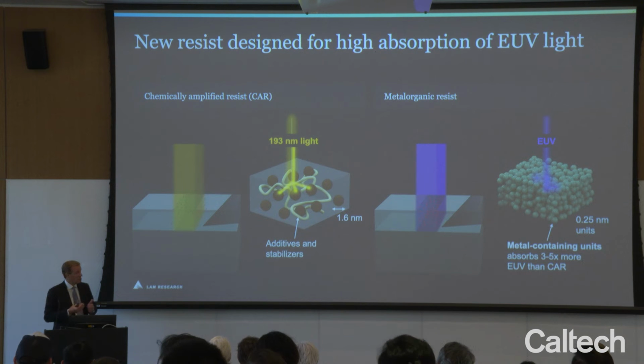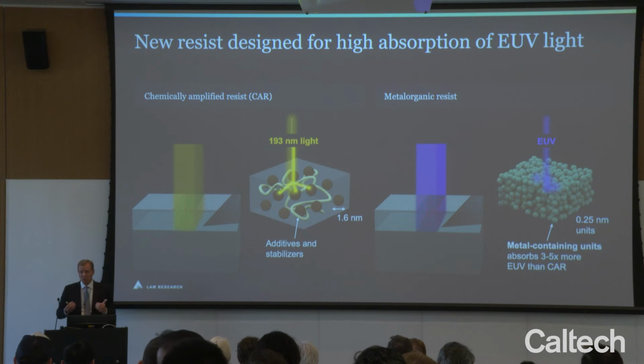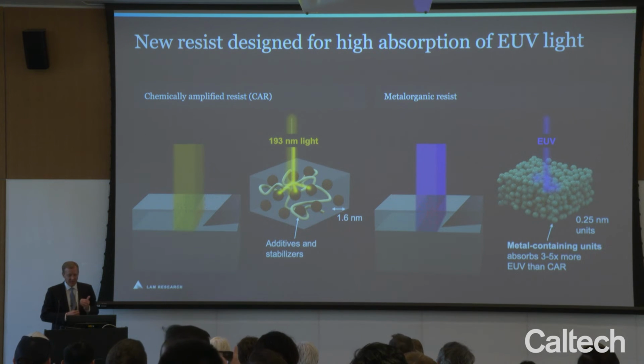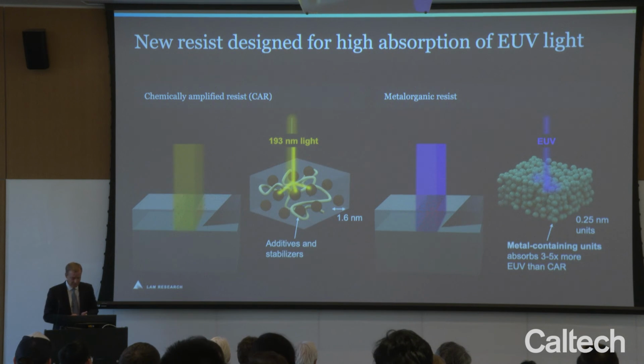We find that compared to chemically amplified resists, they absorb 3 to 5 times more effectively the EUV photons that are hitting the wafer. And just based on that increased absorption, you'd be able to shorten the exposure time and reduce the cost of lithography at advanced nodes.